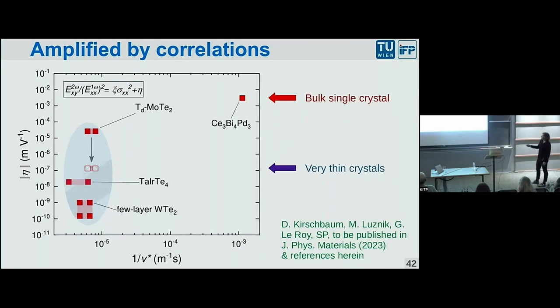And we relate this being larger to the flatness of these linear bands. So the linear bands, really, the flatness is the slope. The slope of the band is the inverse velocity of the electrons, and that's a measure of how strong the interactions are. And we see that the shaded line here indicates a very big effect for a very flat slope or very large one over slope. Okay, so it's really directly seen here that if you have strong correlations, this effect is very strongly amplified.